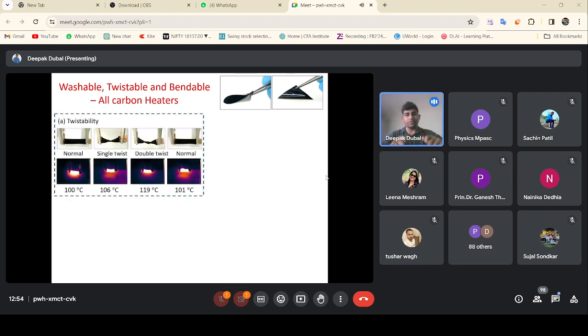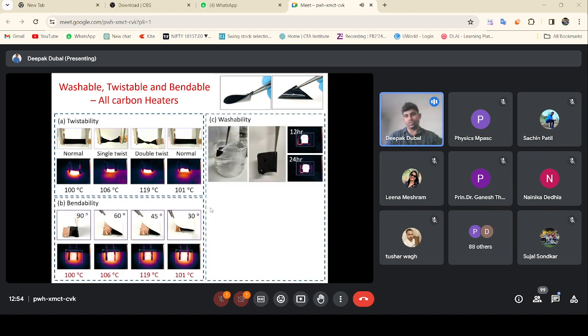So you can see that we developed heaters which can go to 100 degrees Celsius or even 120 degrees Celsius when we apply a very small amount of voltage, somewhere around 10 to 12 volts, and the current is somewhere around 15 milliamps. So that's what we are using. You can twist these heaters, you can fold them, you can even wash them. It means we can wash the car. And these heaters are simply like stickers, and they can be stuck anywhere in the car. You can stick them on the dashboard, on the internal part of the car, and even on the seat. So this is very interesting.